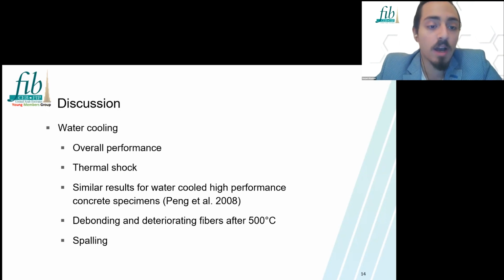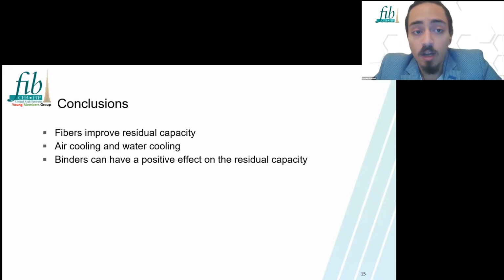All of these combined will increase the risk of spalling, and we did have some samples that spalled, especially at 800 degrees, post 500 actually, because the concrete itself, the inner core of the concrete, starts to deteriorate and the top surface as well. So the elongation of the steel fibers combined with the thermal shock of the water addition, both of them were very severe. Now to conclude our presentation, we can clearly see three main points: that the fibers in fact improve residual capacity at every temperature.